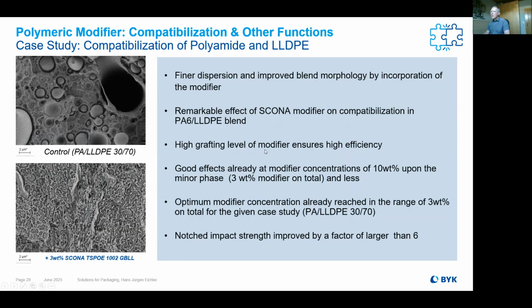And if we look now at a picture taken with a microscope, we have here the control sample, and you see these big bubbles here without any bonding to the matrix. That means these big bubbles are the polyamide, and the matrix is the LLDPE. And like I said, there's no real bonding between these two polymers. Now, if you work with our SCONA modifiers, you see, of course, the difference. The particles are smaller, and you see it starts really to bond to the matrix. So the polyamide is really bonded with the polyethylene, and that's exactly what you saw in the slides before in the improvement in mechanical properties.